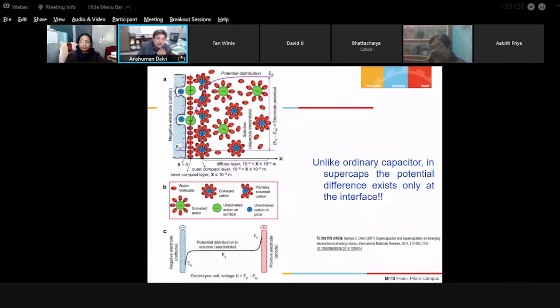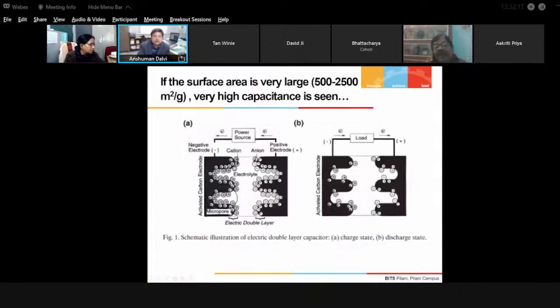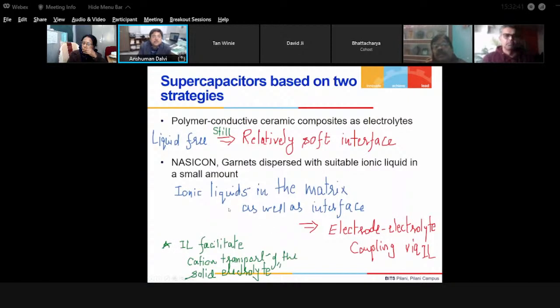Everything which is happening is because of the potential gradient at the Helmholtz layer, for example here or here, and in between there is no electric field existing in the middle portion of the electrolyte. So if you have a huge surface area, then you can achieve huge charge storage at the interface. These are electrostatically attracted charges. There are no Faradaic processes happening here, and therefore we get a huge capacitance, provided you have a huge surface area at the interface.